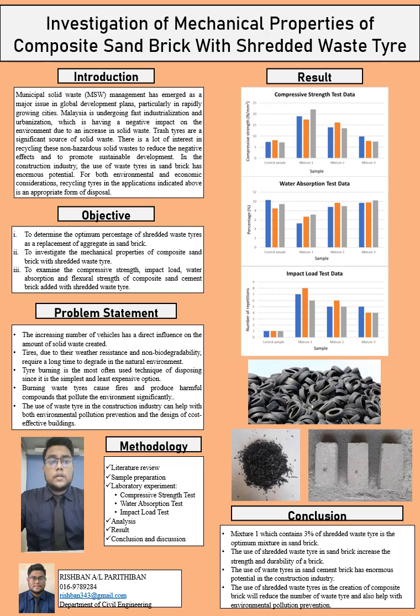Now let's see the methodology. First of all, it is started with the literature review, then followed by sample preparation. 3%, 4% and 5% of shredded waste tire as replacement of aggregate were used as sample in this thesis. For the laboratory experiment, compressive strength test, water absorption test, impact load test were conducted. Then, results from the laboratory test were collected. From the result collection, analyses were made. Finally, conclusion and discussion are done.